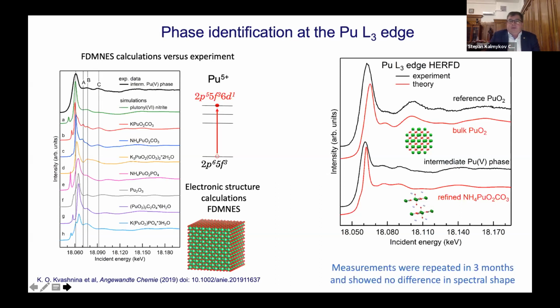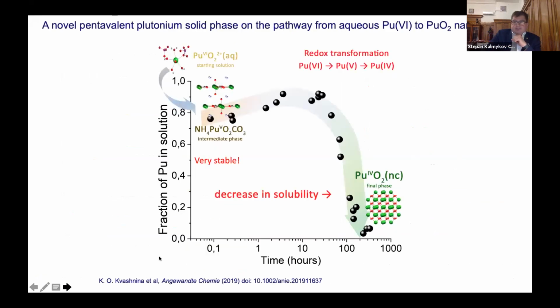The important thing that I already mentioned is that the kinetics of formation of this intermediate phase is quite slow. Compared with plutonium-3, plutonium-4, and plutonium-5, where within a few minutes we have the green precipitate, in this case it could take up to several months. In measurements repeated after 3 months, we still have this plutonium-5 in the system.